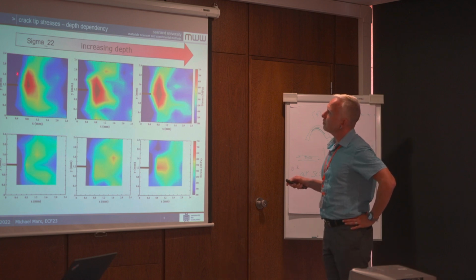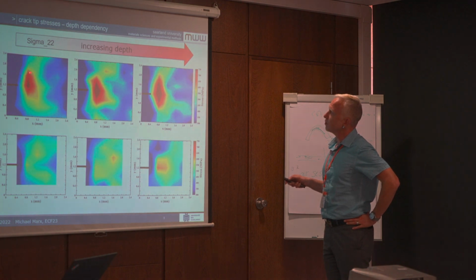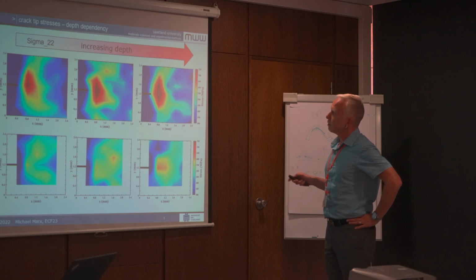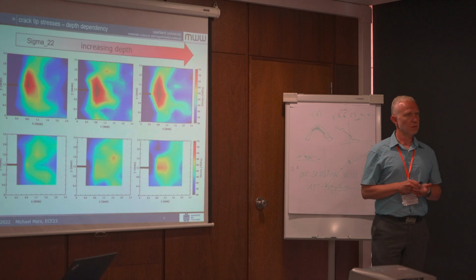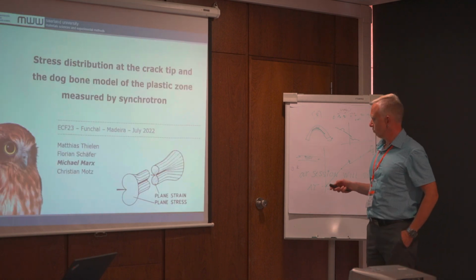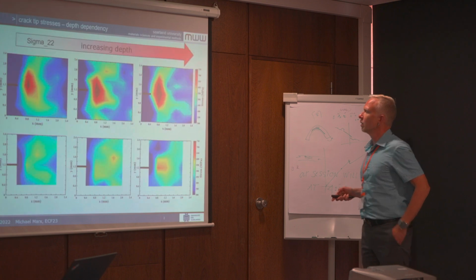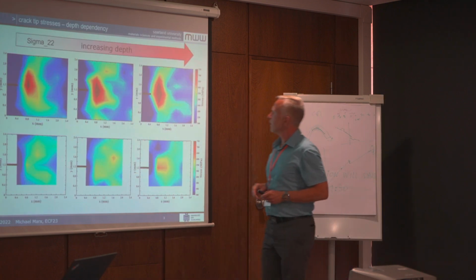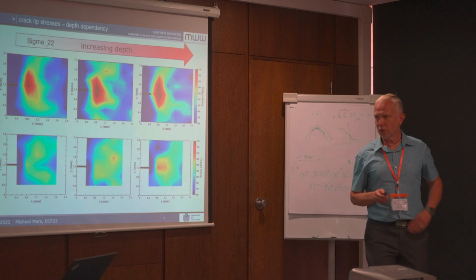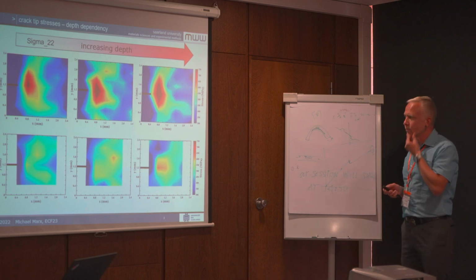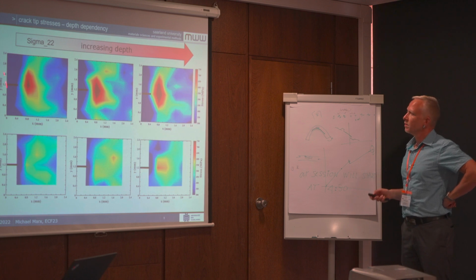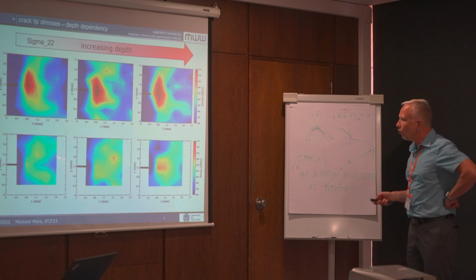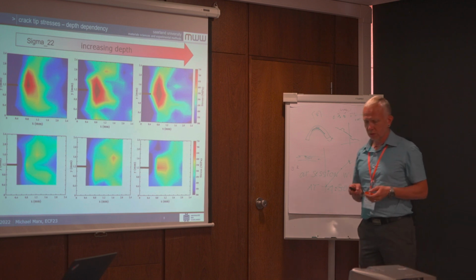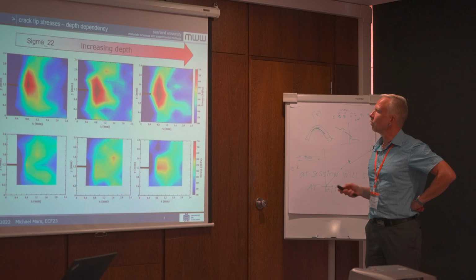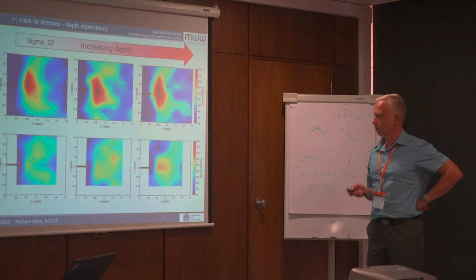Here you see the stress distribution at the surface, and if you go to a deeper position then the plastic zone is increased, whereas according to the model it should be reduced as you go deep inside. This was the last position measured at the beginning. We think this is not what we would have expected, and this was also found after the overload. Then the plastic zone is reduced due to the residual stresses after the overload. But we will focus here on this.